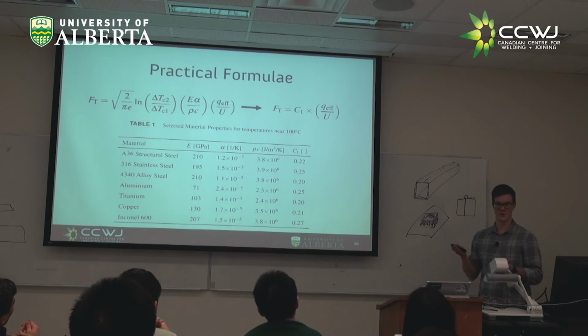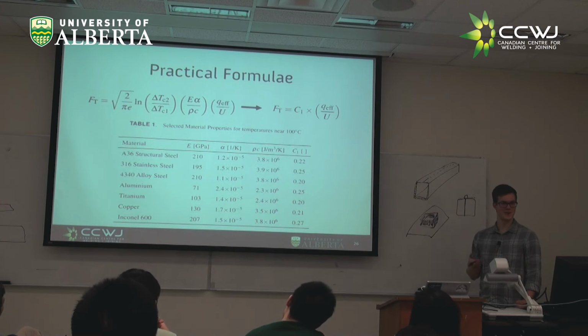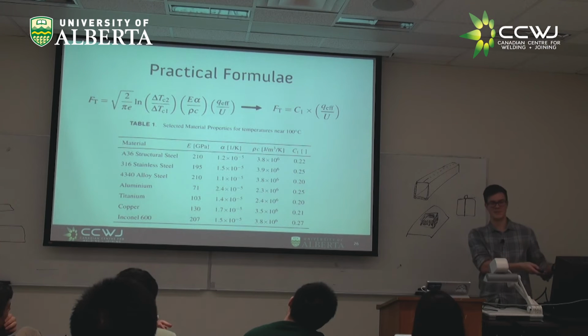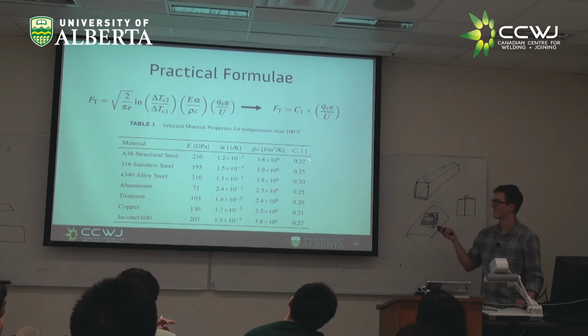And they're getting a variation from 0.15 to 0.25 because they're not all using the same geometry, they're not all measuring things perfectly, and they're not all using the same strength steel, so there might be some minor variations there. But they came up with this understanding. But if you look at those papers, you would probably rightly say, that's all done for steel. I have no hope in using this for aluminum. How could it be the same?